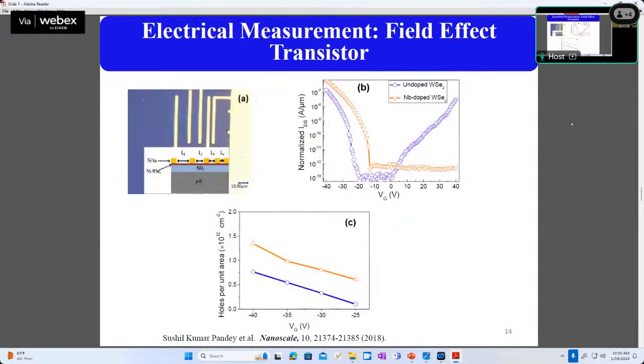Now, we fabricated a field effect transistor with these materials and with different channel lengths. And we found that for undoped WSe2 and niobium doped WSe2, the undoped one has ambipolar nature, means it works sometimes as p type or n type. Sorry, ambipolar nature, not amphoteric. And the doped one has p type nature. If you look at the gate voltage versus drain current graph, high current at a negative bias means it is showing p type conductivity. So this is basically a p channel FET.